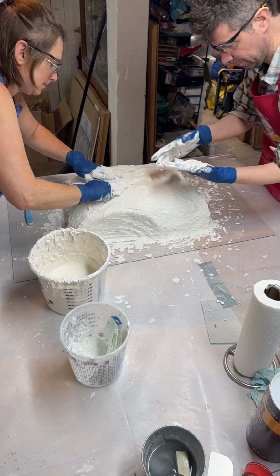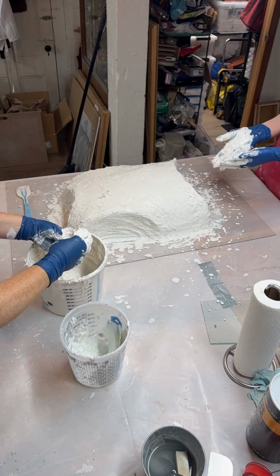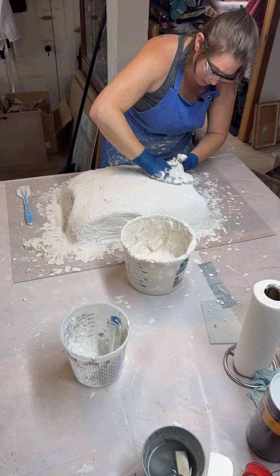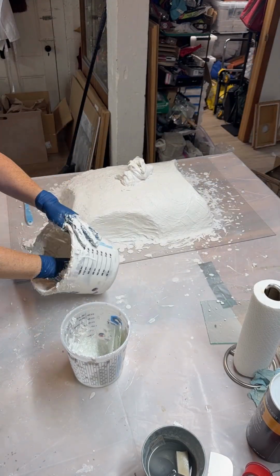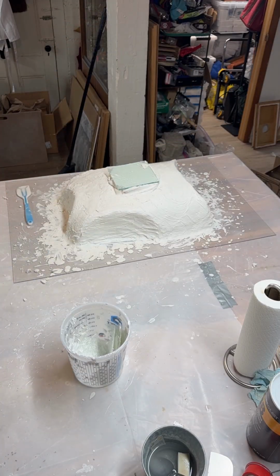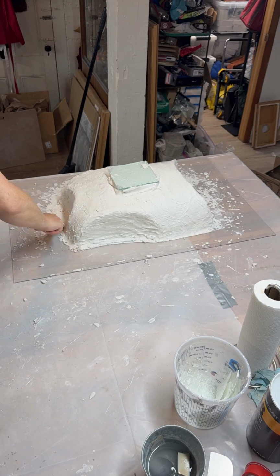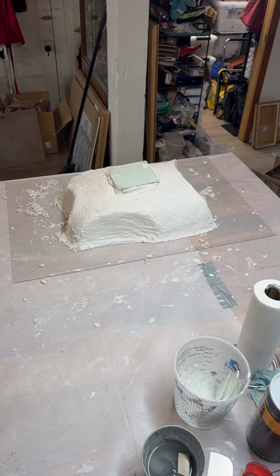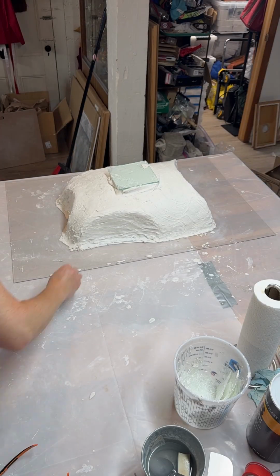With non-traditional Pate de Verre, your mold doesn't need to be much thicker than ½ an inch, but it needs the fiberglass layer of stability to survive the firing process. I use the remaining plaster mix to make a foot at the bottom of the mold so it will stay level in the kiln for firing. One last cleanup, and we're done with the plaster mold.